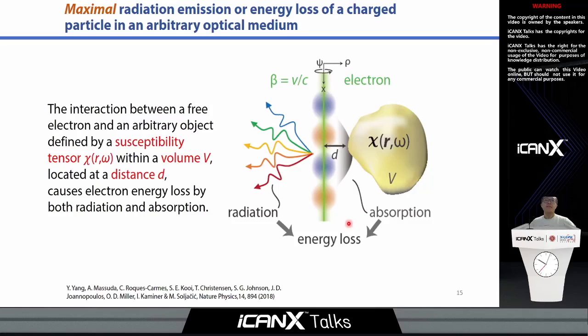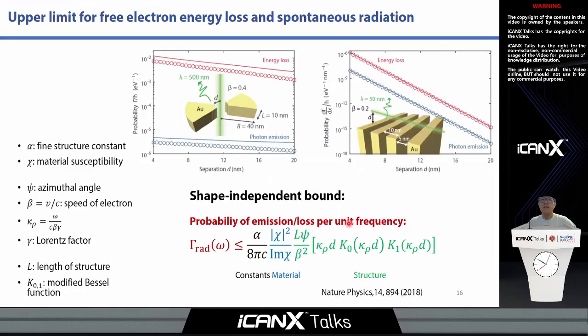I'll skip the math here, but I will directly show you the result. What we obtain here is that the emission probability per unit frequency must be smaller than this quantity, which has some physical constants, a material factor in blue, and the structure factor shown in green. And we test this upper limit by numerical simulations on different structures. For example, here is the bow tie antenna with optical emission, and here is the grating that emits radiation in the deep ultraviolet.